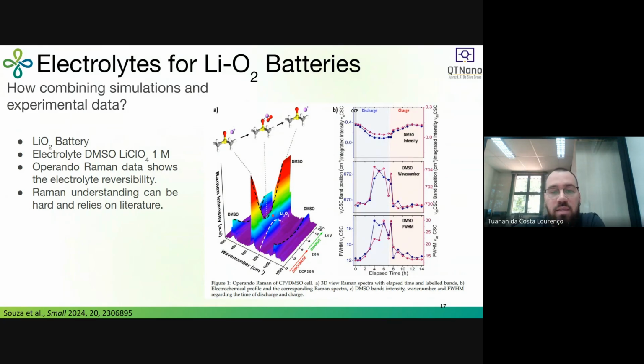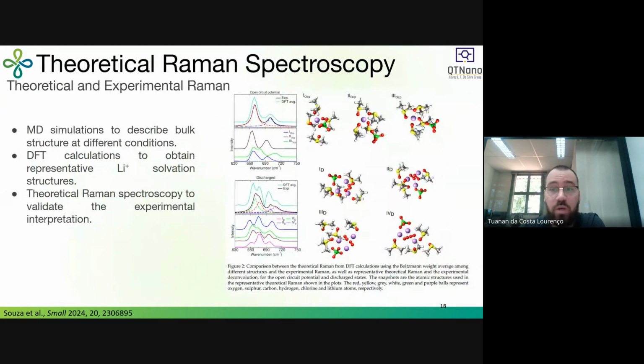So to try to understand and investigate this behavior, we calculated theoretical Raman using DFT and MD simulations. One problem when we do spectroscopy using DFT or any kind of first-principles simulations is that when we do the experimental measurement, we are looking at the average of different solvation shells. So we have a really good sampling of the solvation shells within the system. However, when we do this in theory, we are looking at a smaller number of solvation shells. So sometimes it's hard to describe the behavior because we do not have a good sampling of our atomic coordinates.